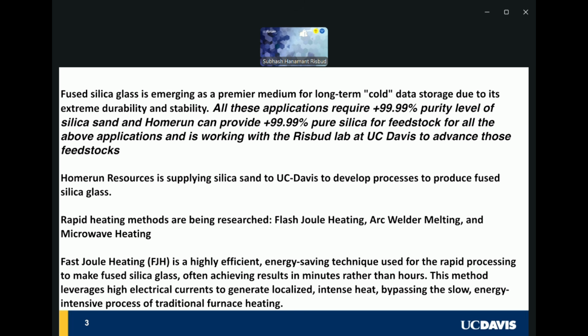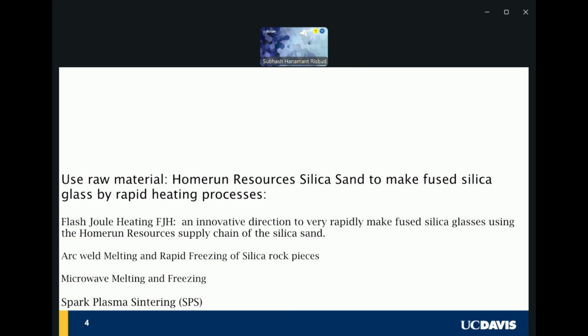The problem with silica, of course, being an insulator, is that you need to surround it with something that will actually conduct. So, we've done a methodology where we use the sand by 3 different methods, as I said, and then I added a 4th one to this list, which we have been doing for many, many years at Davis, called spark plasma sintering, which of course has spread all over the world now. So we started this in the 1990s timeframe through a machine donated to us from Japan called Dr. Sinter, which basically says you can convert a powder to a dense disk in minutes rather than hours. And microwave melting and freezing is something newer, which we're just starting. Arc melting, of course, I just mentioned, where you put rock pieces in, and I'll show you some limited, early experiments we've done with that. And then, of course, flash Joule heating. So those are the 4 methods I want to talk about, the focused goal being to make fused silica glass.